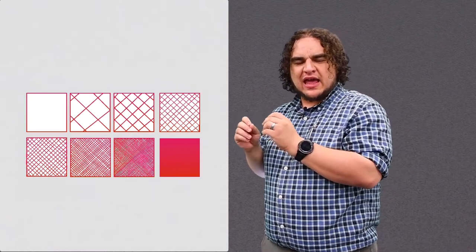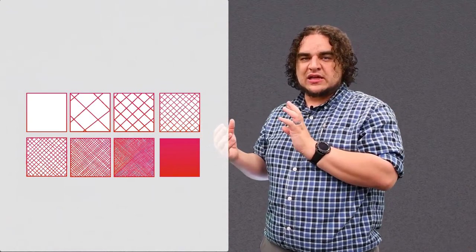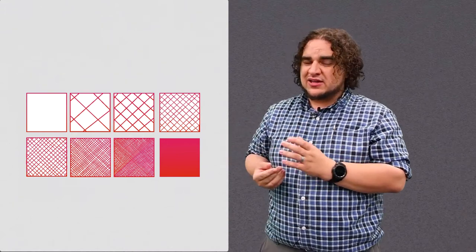Another structural design consideration is how our infills are actually going to make our model stronger or weaker. You might need a piece that has to be close to solid to hold up to forces that would act on it, if you're using it for a mechanical project or something that's going to hold weight. So you would think about making things not too thin, with zero infill, or not too thick, to be more or less solid. In 3D printing, typically we've found that you don't get much more strength out of your infill patterns once you hit about 50 or 60% infill. At that point, the material is probably going to yield or break, even if it had been solid. You actually gain some ductility and flexibility from your print by not having it be solid, but still have the impact strength you would typically get.